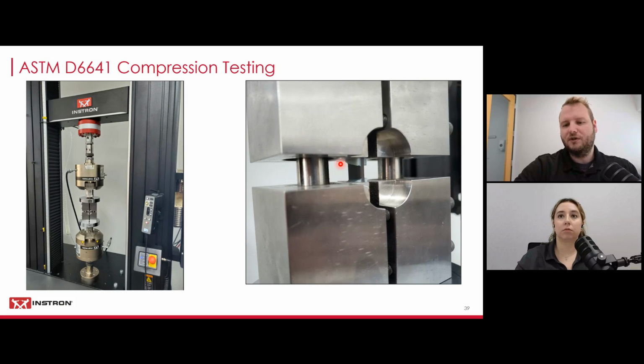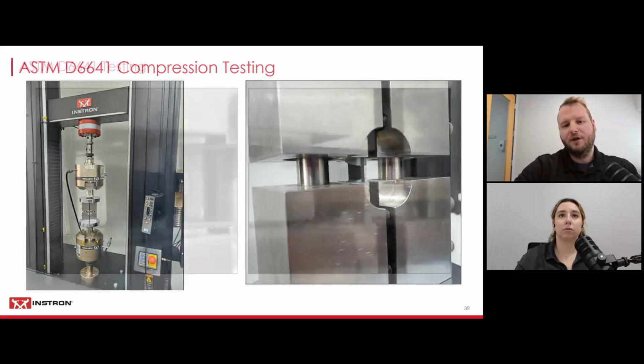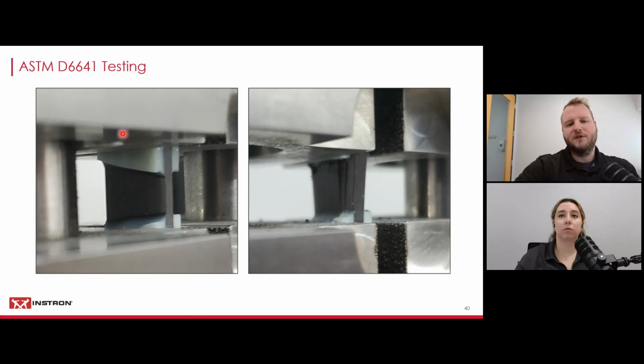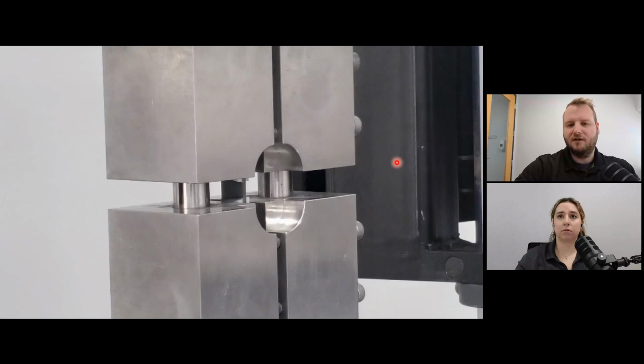So you need to use some other kind of transducers in the form of strain gauge, which I will show you as well, but I first want to look at a complete test here. So this is the specimen zoomed in before the test, and then this is after the test when the specimen failed. You can see here it failed in the gauge section, and we have a video of the test. In the beginning, the video is sped up, and you'll actually see the fixture moving down. So all of that compliance within the fixture building up. So the fixture actually moves. And then right before the specimen fails, we slowed down the video so you can see the failure, which should be occurring now. There you go.